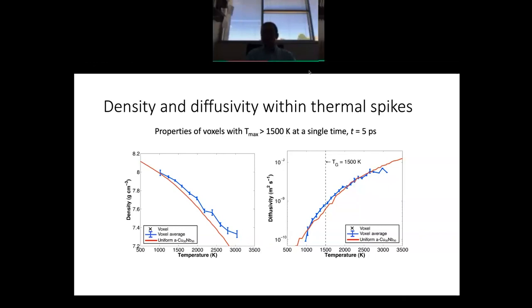I hesitate to shotgun this question. I guess the short answer is I don't know. But the somewhat longer answer would be that we've made a lot of approximations when we characterize these thermal spikes. So for one thing, the thermal spikes do not have a uniform internal temperature, right? Their temperature when they're generated is initially non-uniform. The second thing is that there are actually many thermal spikes that are close together, right?